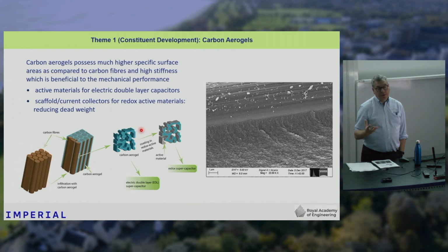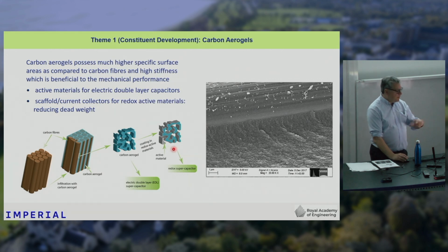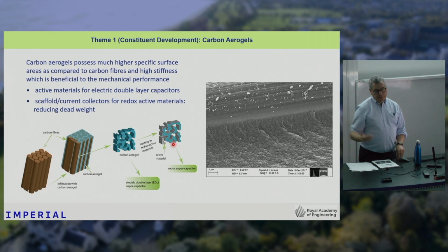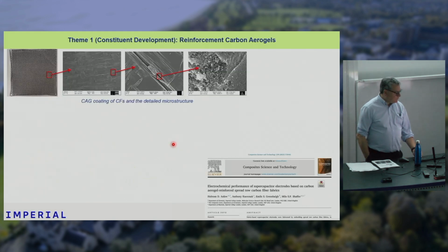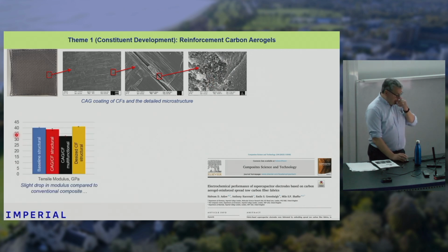The problem with it is it's really brittle. But the nice thing about using the carbon fibers is they act as a scaffold. So rather than having a powder, the carbon aerogel is supported by the carbon fibers, and we can produce laminates. I think the largest we produce is an A4 size laminate, which is continuous carbon fiber with a continuous aerogel throughout it. Then you can start to put other materials onto the aerogel to improve its energy storage capacity. This is a laminate we've made. Zooming in, you can see the aerogel structure. And then we've done some comparative studies. This is showing you a baseline composite, a structural resin with carbon fibers.